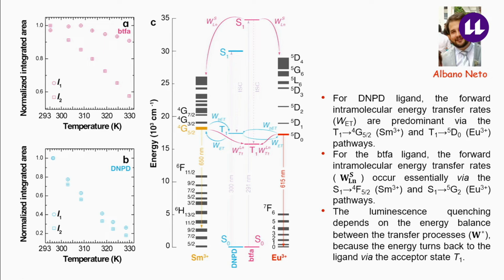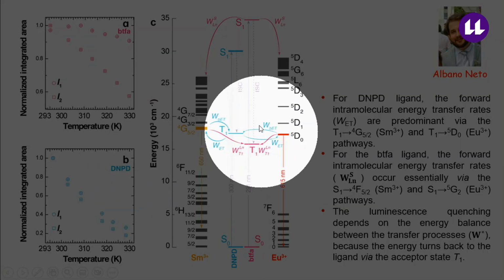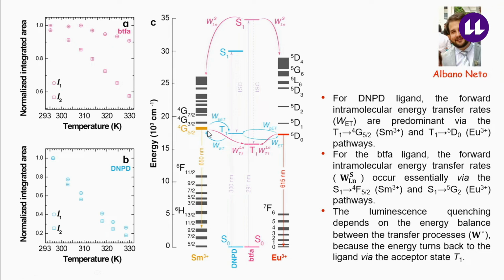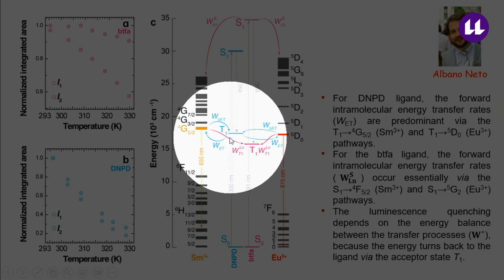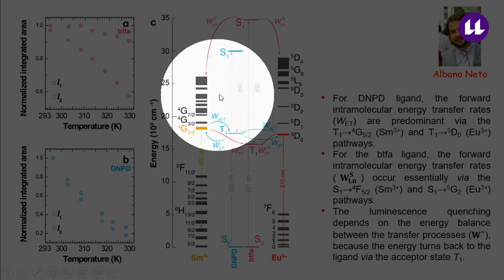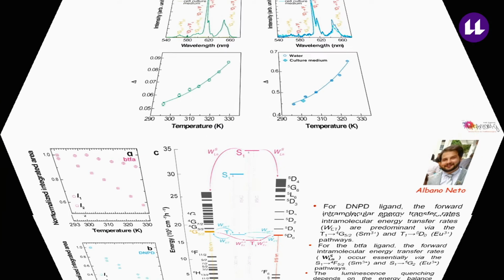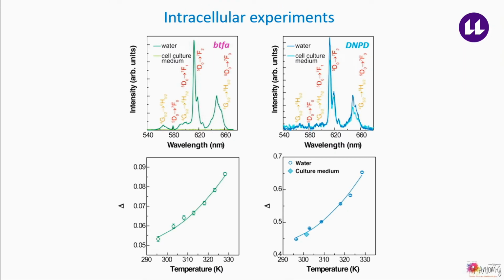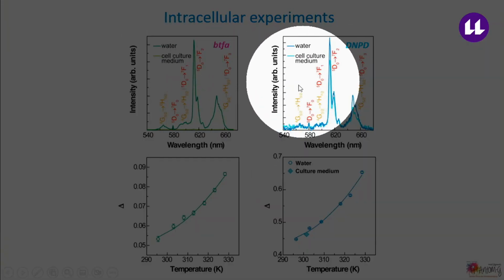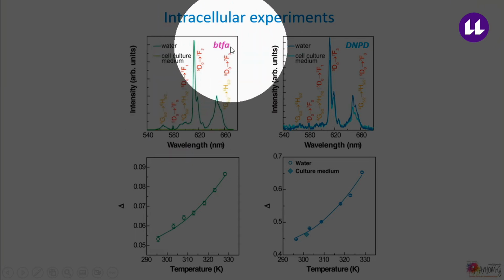This work was done by Albano Neto, who is here, who can explain the variations in the intensity due to these different mechanisms from the ligand levels to the lanthanide ions. We have not only energy transfer from the ligand levels to the levels of the lanthanides, but also the back transfer, which is also temperature dependent. So the main point is that we were able to explain this temperature dependence.